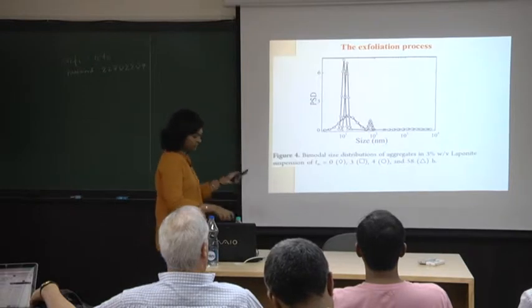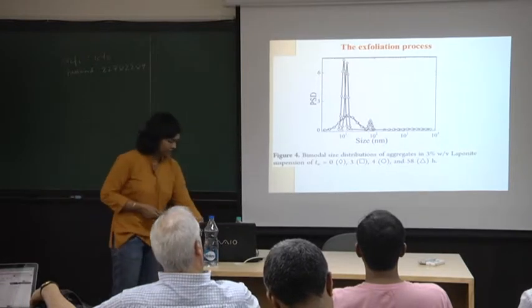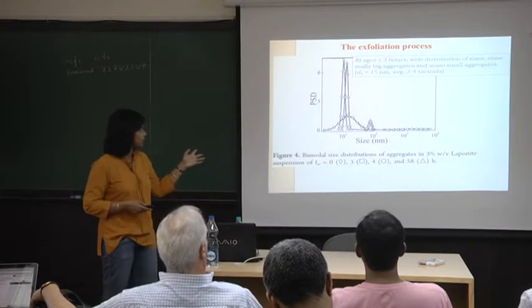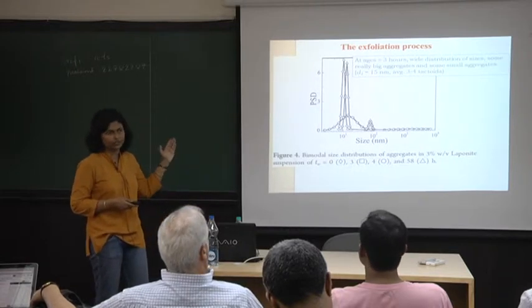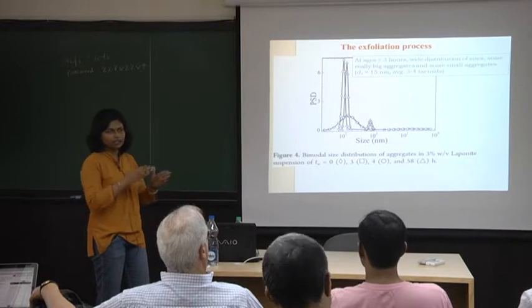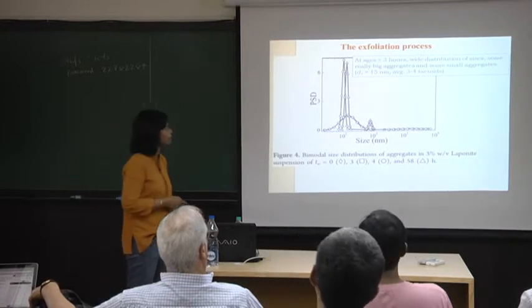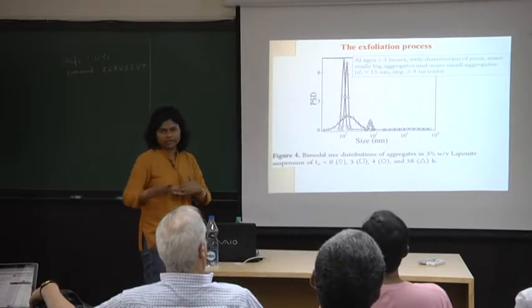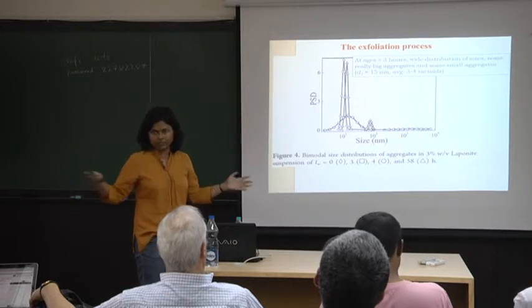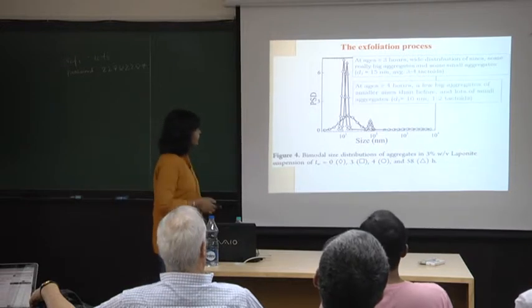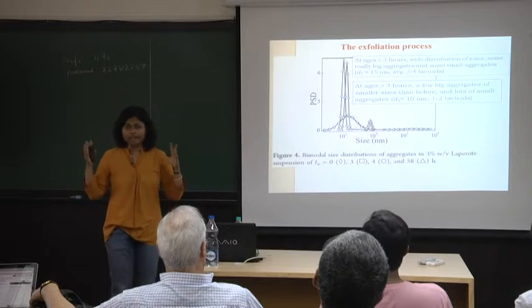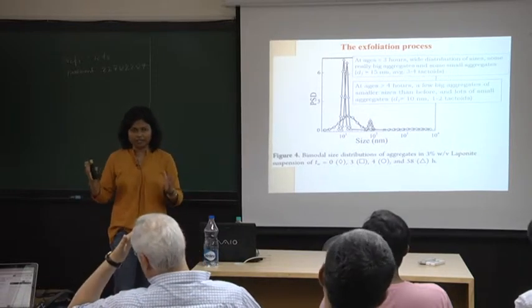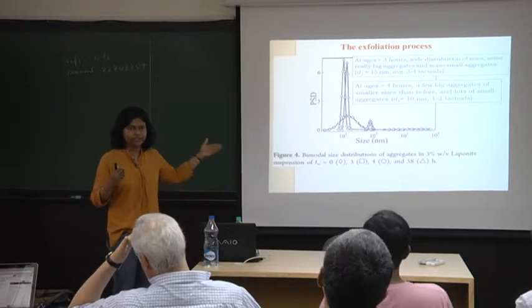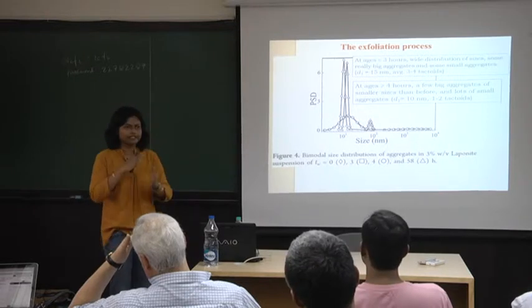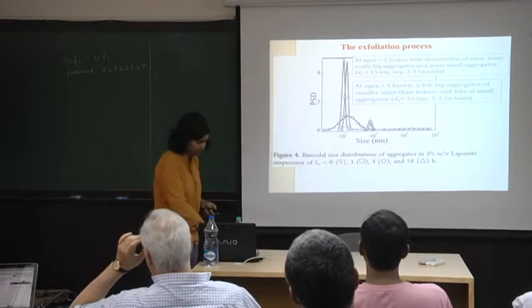Okay, so we've also made measurements. This measurement that you see is done by using ultrasound attenuation. So we basically sent sound through the sample, and we looked at how much attenuation happened. You can model the attenuation spectra, and you can come up with a size distribution of the particles. And we do see that at the lower ages, you have big stacks of particles, which eventually with age, that is with increase in this TW, split up into much smaller particles.